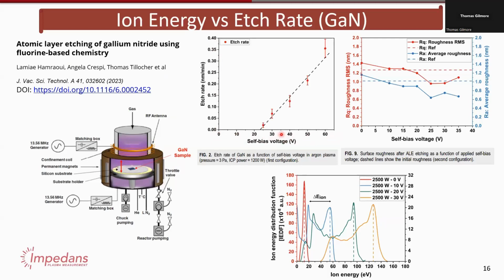Now, self-bias voltage is not quite ion energy, but it's pretty much the same idea. What you're missing here is plasma potential to get the ion energy. But in any way, the concept is that there's some point at which you start etching the materials when the ion energy is high enough, and then it starts increasing with that. So this is something you need to understand for whatever material is in your chamber. Okay. Surface roughness also depends on the self-bias. That can change depending on that as well.